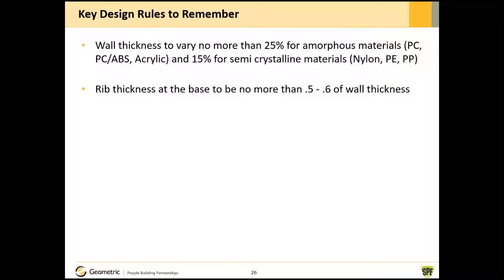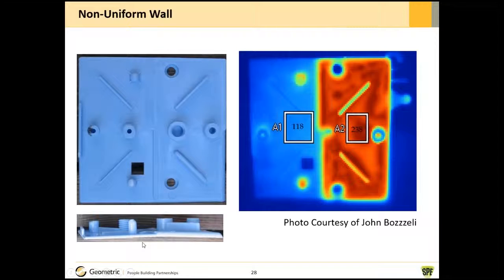So what happens if you have a non-uniform wall? This is a part that has been by design made into a very rapid transition in thickness from the left to the right. The right is 200% of the left in terms of thickness, and this is how it comes out from the mold. This is infrared photography of the temperature of the molded part. You can see on the left side, the part has a lot less heat content and cooled down very rapidly. And when it comes out of the mold, it's at 118 degrees C. And the right side has a lot more heat content, which is still cooling down, and it's 238 degrees.